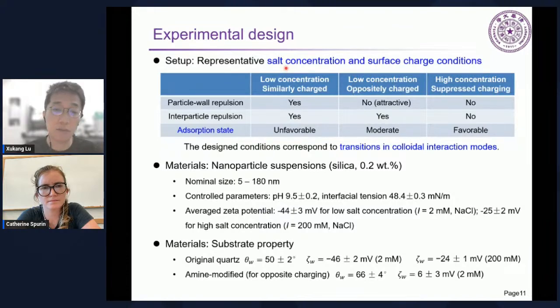Because of the time limit, I won't go into them too much, but basically we just vary the salt concentration and surface charge conditions, which are very important for interactions between particles and the surface, and also particles and particles. So you can imagine that when both repulsions are very strong, then adsorption will be very difficult to occur, and thus wettability alteration will be influenced. As we vary the salt concentration and change the surface charge, we will have different colloidal interaction modes from unfavorable to favorable. And we just select 3 representative conditions to investigate the trend.